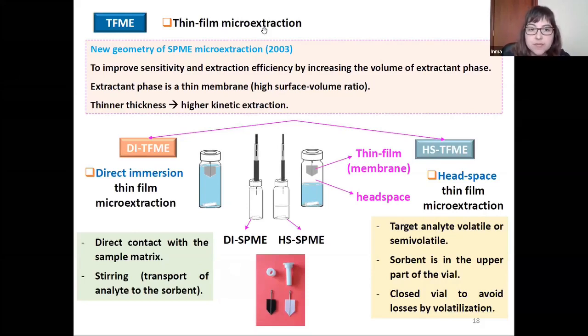In the case of direct immersion, the solid phase is in direct contact with the sample, and the stirring of the solution allows the transport of the analytes from the sample solution to the thin film. In the headspace thin film microextraction, the target analytes have to be volatile or semi-volatile. Sometimes a derivatization step could be used to volatilize these elements. Thus, the sorbent is in the upper part of the vial, as we can see in the headspace of a closed vial, to avoid losses by volatilization.